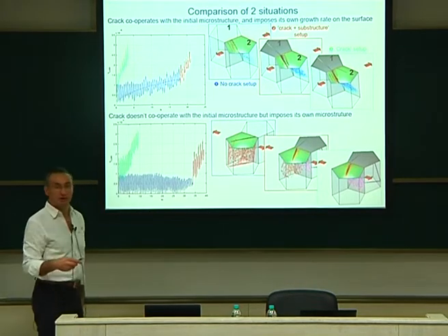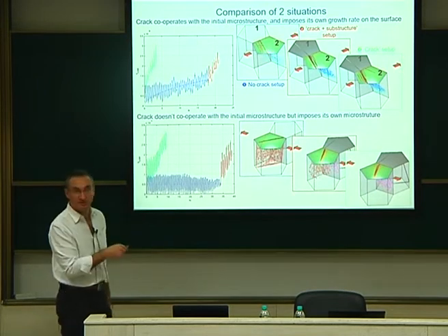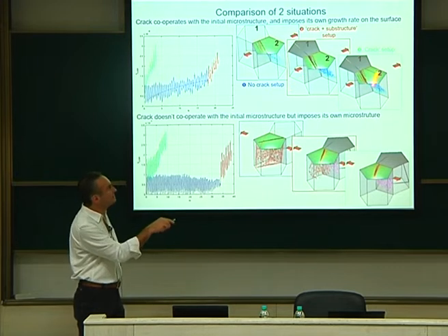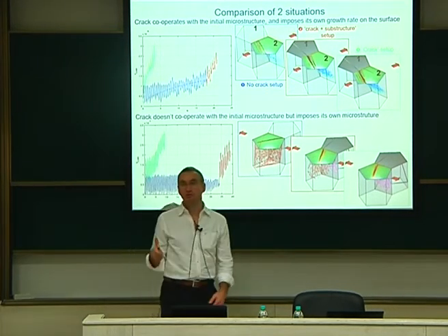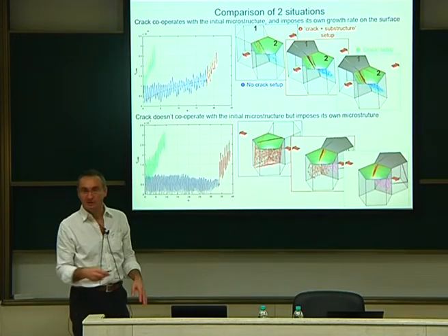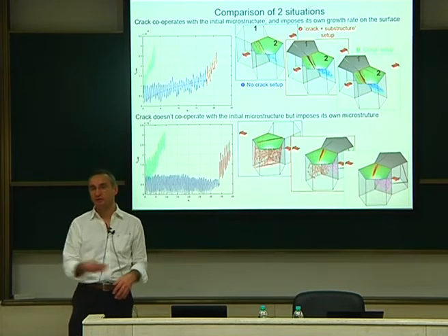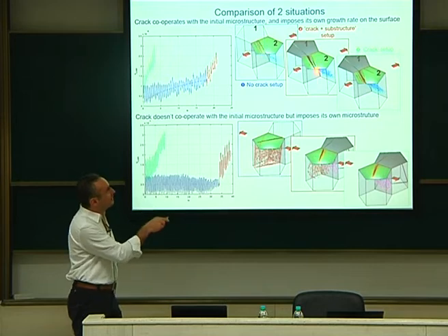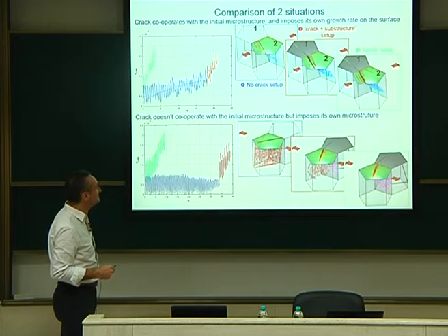Initially, like yesterday, a single source was enough to develop the persistent slip band in that grain. Then because of the crack, we put the sources here. Now we have the sources, and we see how it propagates. We know that for fatigue, a single source is enough, accommodating what you apply. You can put the 12 if you want, but then they will not move, actually. They will be totally reversible. They move up and down, and they don't care. So we put a single source, it leads to that. Here we put the crack plus the sources, and it leads to this. This is the idea.